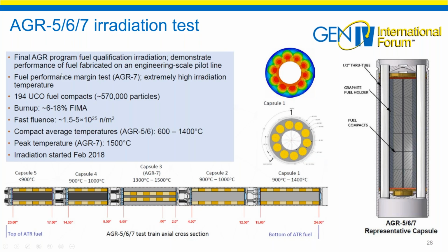And again, we have 5 capsules. Capsule 3 is our margin test, our AGR 7, where we have very high temperature fuel. The peak temperature is at 1500 C. We have compact average temperatures in 5 and 6 in the other capsules between 600 and 1400 C to bound what would happen in a gas-cooled reactor. We're seeking 6 to 18% burnup, and we have 194 compacts. So it's over 500,000 particles to get good statistics.